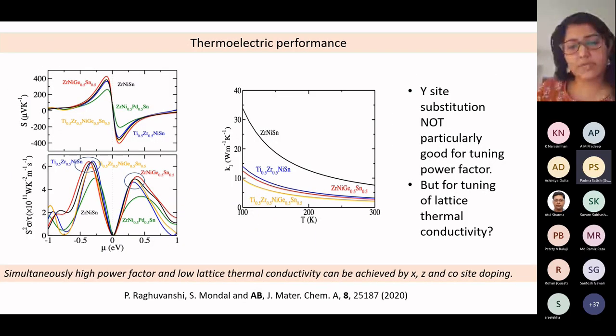So therefore we proceeded further, and we showed that is true. So the Y site substitution is not good, but the X and Z sites are. And therefore, what should one do? If you also look into the lattice thermal conductivity, it is quite lowered in these materials, but that's not the only thing that can be done in this type of materials.